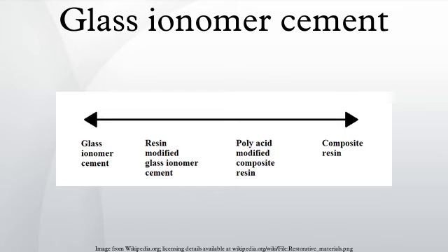They bond directly to tooth tissue by the interaction of polyacrylate ions and hydroxyapatite crystals, thereby avoiding acid etching. In addition, they have an anticariogenic effect due to their fluoride leaching ability. The evidence from a systematic review of clinical trials suggests no difference in the failure rate between resin-modified GIC and resin-based adhesive for orthodontic bracket bonding after 12 months, but favors composite resin adhesives after a period greater than 14 months.